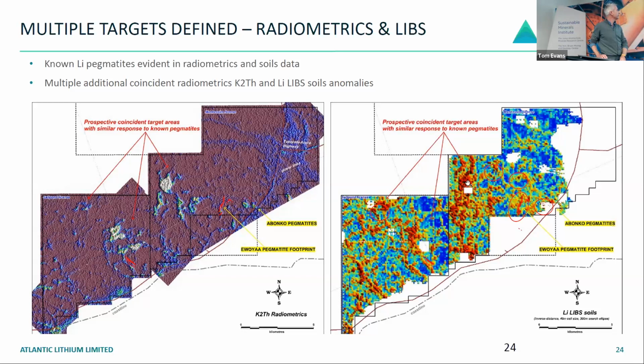And what we actually think is happening is this is also full of mica, and that mica makes its way into the drainages, so it's a resistate. Then when we collect our soils in that fine fraction and produce the puck, you're actually getting all those micas aligned. So you have this surface of mica that you're analyzing. And I think that's what's inflating the samples around Afrangwa and highlighting the drainages. Nonetheless, it is a targeting tool and it has worked for us. It's delivered multiple new discoveries that we've drilled and grown our resource over time. And it's a tool that we're still using now to explore the Salt Pond license out to the west here.